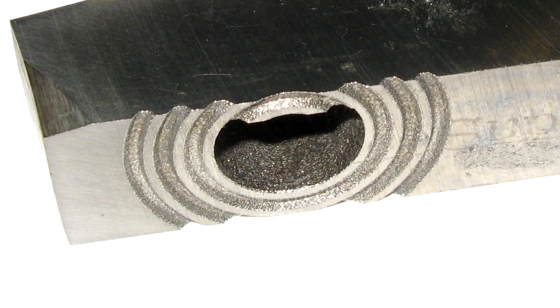Now you can get a very fine finish, but it's still and always going to be a matte finish, class P. Now the surface finish you are going to get is about a 63 micro-inch, which is a good finish if you were turning or milling and that kind of operation. So it's at least equivalent to what you can get with traditional machine tools, chip producing. If you're cutting very rough, and that's what we were doing, well, the finish that we got, and here's a picture, is about 125 micro-inches finish. And if you're very attentive and use a finishing electrode and really have a lot of time to waste because it's going to take forever to cut, well, you could get yourself down to about a 32 micro-inch finish, and that would be about equivalent to a reasonably good everyday finish that you would get on a surface grinder.